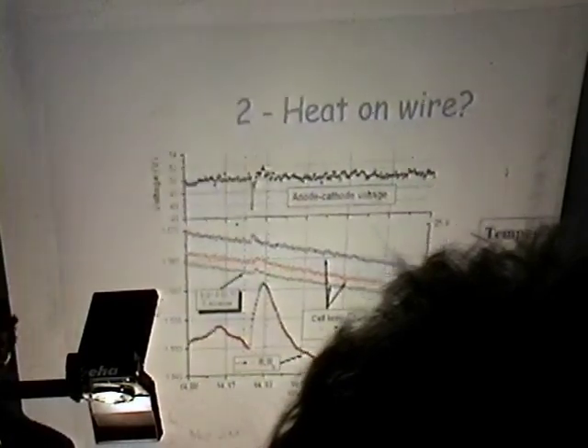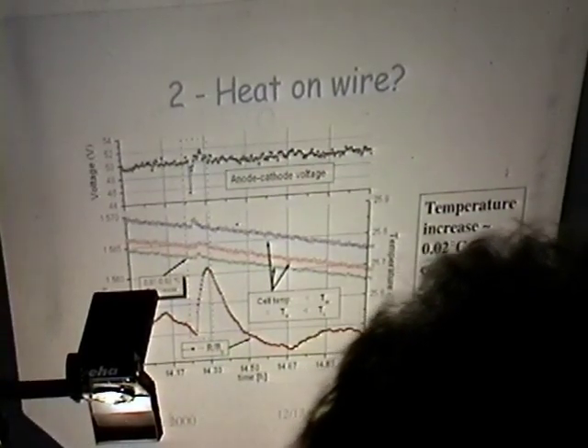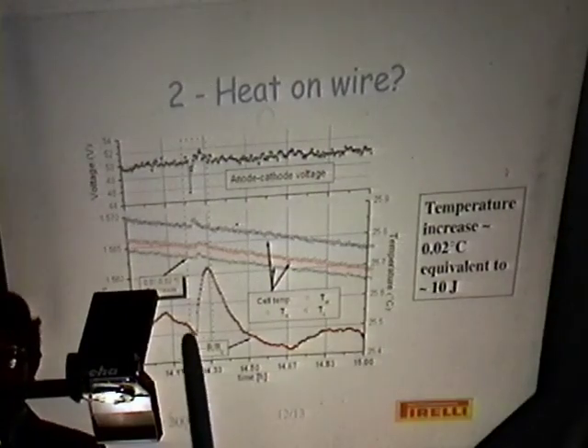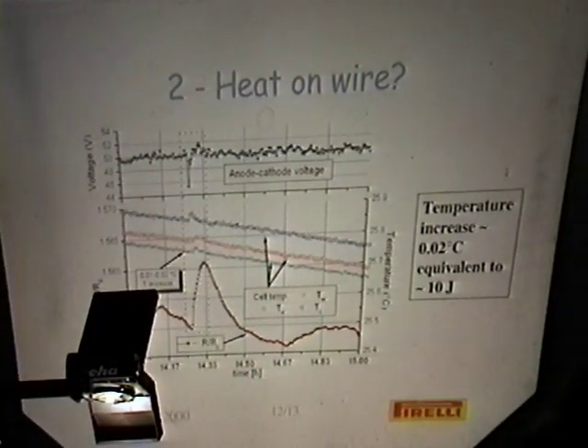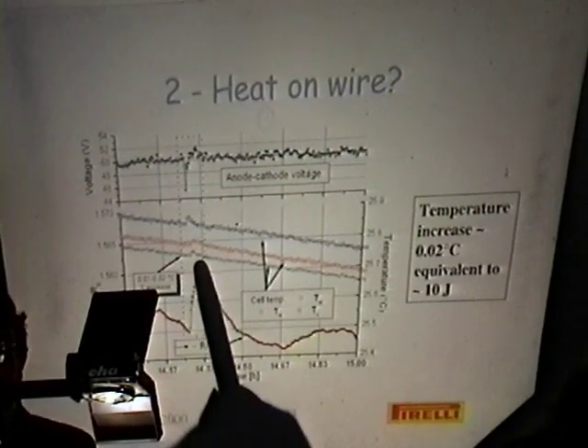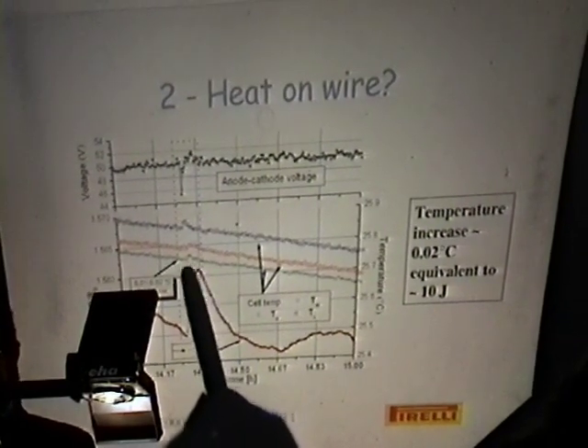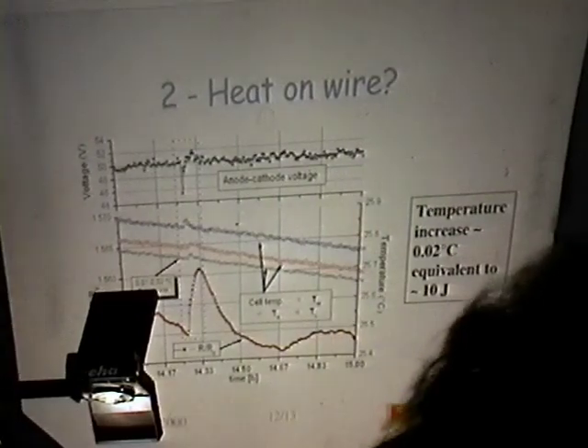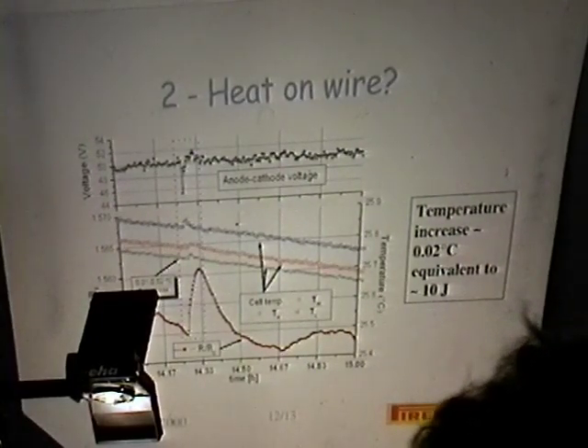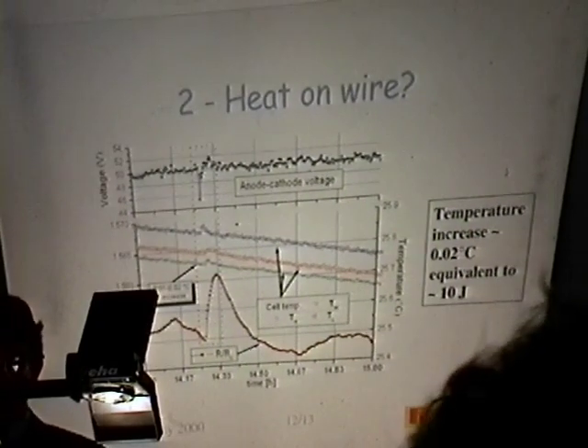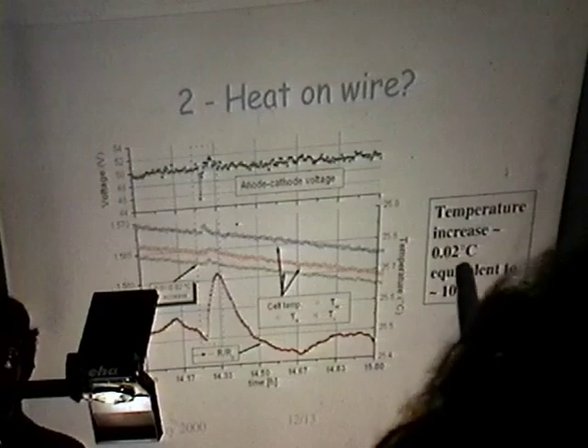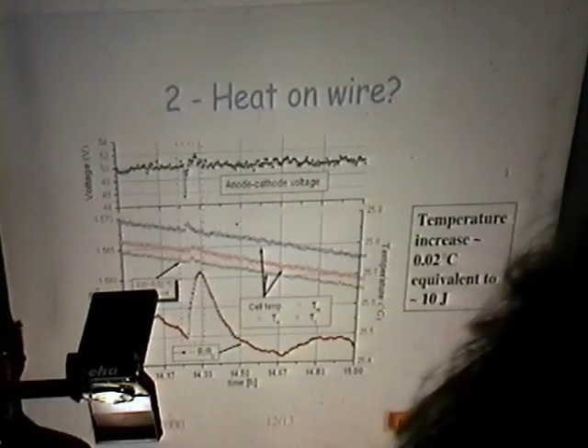Another possible indication, this is an example of the variation of the resistance. We have seen this several times. There seems to be a correlation between the increase of the resistance and a little increase of the cell temperature. These are 3 points where we measure the cell temperature. Our rough calculations show that an increase of 0.02 degrees Celsius corresponds to 10 joules. These are clearly only indications.